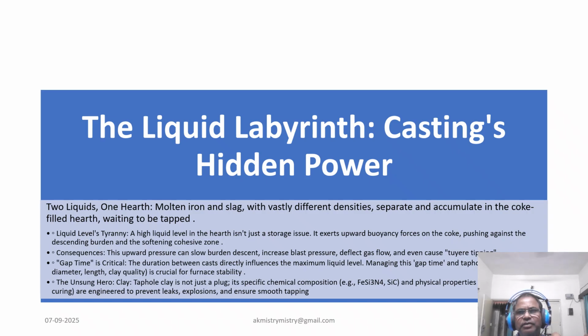The gap time, the period between opening tapholes, is meticulously managed to control this liquid level. And then there is the taphole clay itself, a highly engineered material, not just a simple plug. Its composition, designed for wear resistance and rapid curing, is critical for consistent tapping and preventing dangerous incidents like molten metal breaking through or an explosion caused by water backing up into the blowpipe. It's a constant battle to master this liquid.